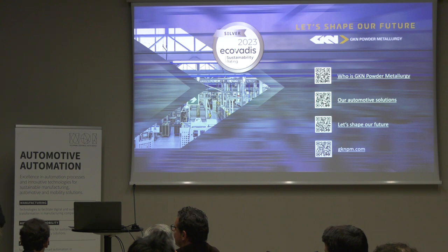Well, this was not the audience for explaining our process in such detail. Usually, when you press the part, you need to lubricate the powder because of friction. We use some zinc stearate, a lubricant, 0.5%. Then you sinter the part up to 1,100 degrees, and everything is burning off.